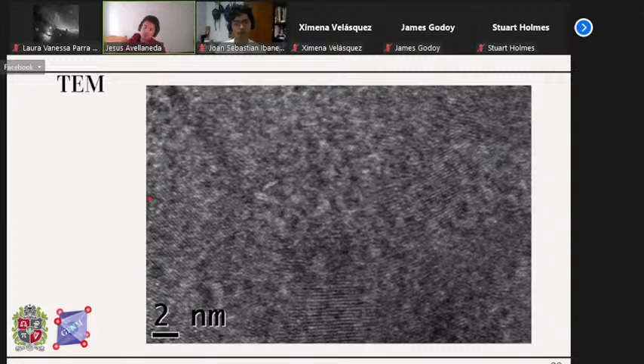Okay, so we also carried out TEM measurements with the help of Ximena when she was doing her postdoc visit, if I'm not mistaken, at Cambridge University. As you know, transmission electron microscopy is a powerful technique that provides detailed information about the structure and composition of materials at the nanoscale. TEM can reveal the material's morphology, crystal structure, defects, composition, and more. In this case, the TEM used is of the Lorentz type. That is, we have a beam of electrons passing through the magnetized sample along an axis, and we are measuring the Lorentz force reflected along the x-axis when the beam interacts with the material.